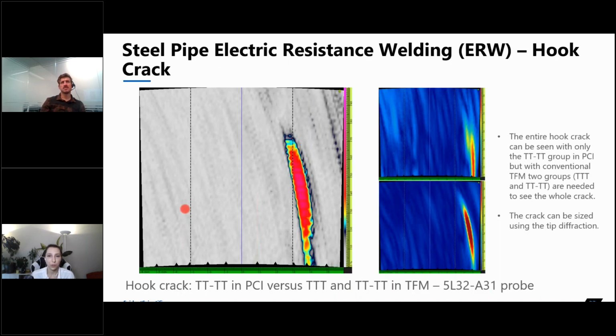And so another application that we found PCI to be very interesting is with ERW. This is a hook crack. So hook cracks are mainly manufacturing defects, really, but they can, in service, start to grow even more. So it's kind of a cold lap. We still call them cracks, but they're very large reflectors typically. Well, not true. They can be fairly large, but they can also be very small. In this case, it was a fairly large reflector, so we were able to see it with the conventional TFM.